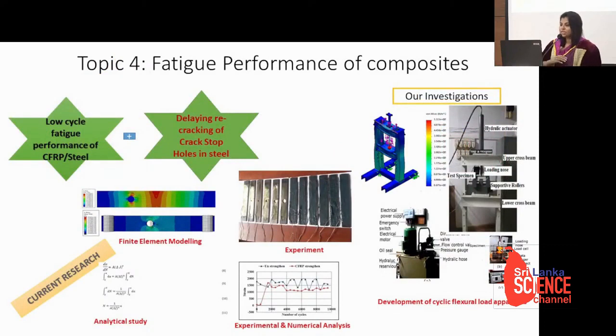Another study is the fatigue performance of composites. The common crack repairing method is the crack stop hole in steel structures, especially for bridges. After arresting the crack using a crack stop hole, there's another problem. With time, when it is subjected to fatigue, reinitiation of cracks at the crack tip is a problem. If we can't again make a crack stop hole, it will reduce the strength of the section. We searched, and no one has addressed that issue. Then we thought we would see whether FRP can handle this problem in crack stop holes.